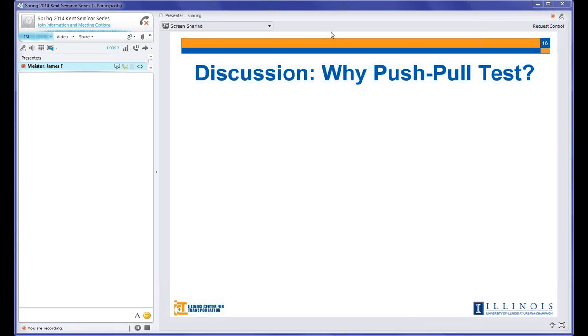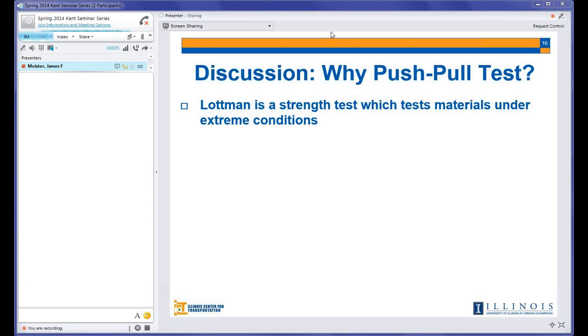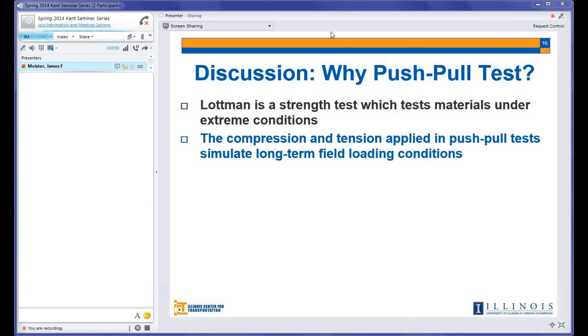As authors, we discussed this a lot. We don't only look at whether a test in the lab is easier or not. There are a lot of benefits we can sometimes get from tests that take a lot of time, such as properties that give us better prediction about the performance and behavior that happens in the field. One of them is that the IDT, or the Lottman test, is a strength test that tests the mixture in very extreme conditions. Meaning, you will never see in the field a pavement loaded until it fails. You will always see cyclic loading coming on the pavement, truck after truck, stress after stress. And this is more simulated in the push-pull test than in the Lottman test, because we apply cyclic loading, tension and compression, until failure.